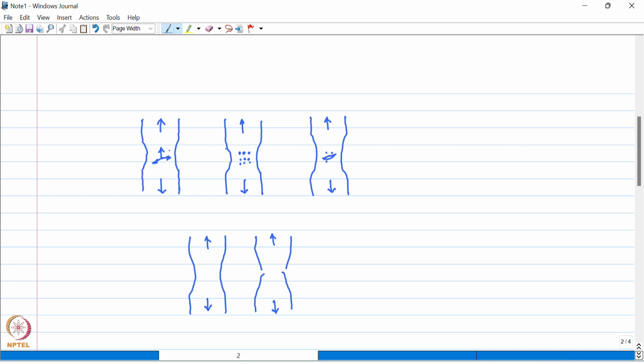So when the necking starts, it will lead to the introduction of a triaxial state of stress around that neck region, as you could see from this particular drawing over here. Due to the introduction of this triaxial state of stress, voids will be nucleated around that region, as you could see from the second image over here. Tiny voids or cavities will nucleate around the neck region.